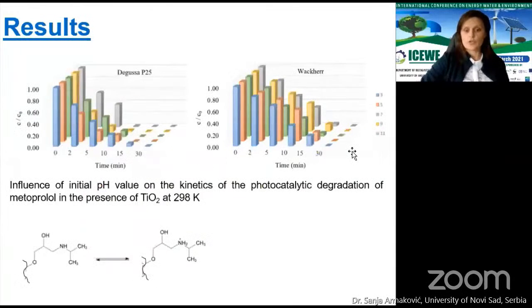The pH of the solution has a significant influence on the electrostatic interaction between catalyst surface and metoprolol. Therefore, we investigated the influence of the initial pH on the degradation in water suspension in the interval from 3 to 11. Significant differences in the degradation rate of metoprolol at different pH have been observed.